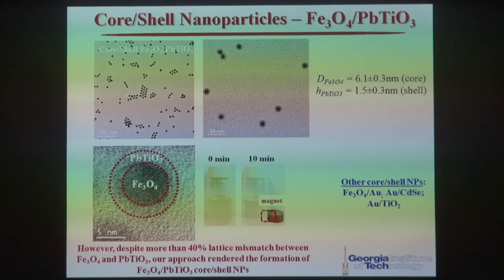So this material actually is quite intriguing. In a sense, when you apply a magnetic field, you create polarization in the shell. On the other hand, when you apply an electric field, you generate magnetization in the core. So it is a magnetoelectric bifunctional nanoparticle. So look at this TEM image. The center of the particle appears dark, coming from magnetic iron oxide, and the shell is relatively lighter, that is lead titanate. And the diameter of the iron oxide core is about 6 nanometers,